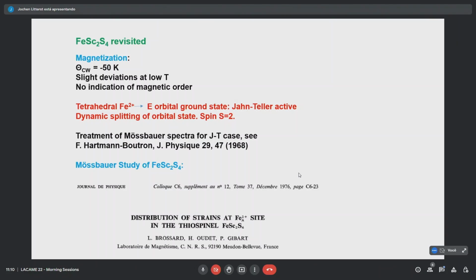Indeed, it shows no magnetic order. If you look for magnetization, it has a Curie-Weiss temperature, which shows that we have magnetic interactions, but we only see slight deviations at low temperature. From that, it's non-magnetic.